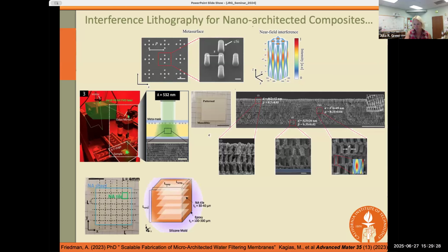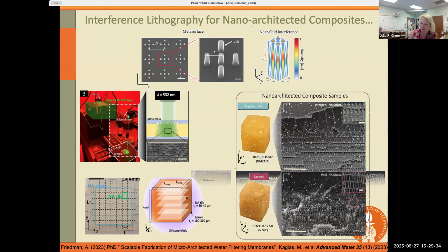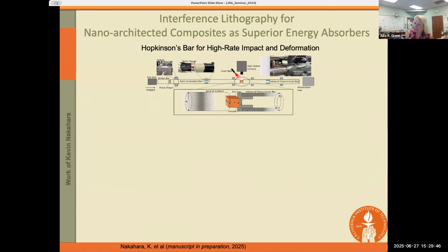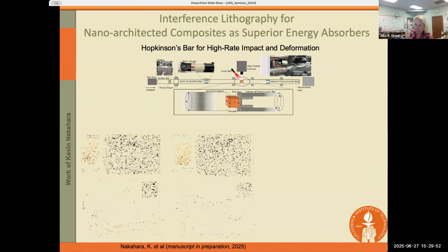And after we produced these nano-architected sheets, my student Kevin put them into composites. And so you can see that layering these composites and interpenetrating these nano-architected layers allows us to further create a composite material, now utilizing these nano-architected layers as structural components. After that, Kevin subjected them to a few experiments in the Hopkinson bar. So these are the special high-rate experiments.